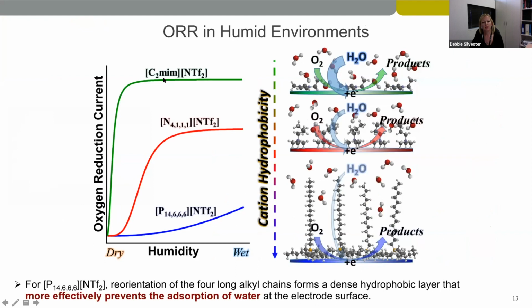So we chose the C2-MIM cation, which is the most hydrophilic, and the most hydrophobic, the P14666, and then something in between, which was the tetraalkyl ammonium. And we did an AFM study and showed that in the presence of moisture, at 40% humidity, the ion layers were disrupted in the case of the first 2 cations, but at 40% humidity, we still see this nice ion structuring at the electrode in the tetraalkyl phosphonium.